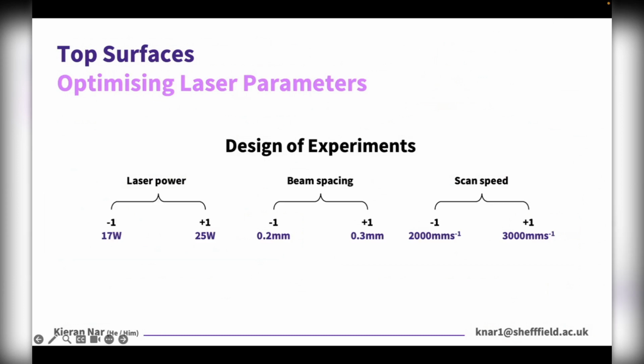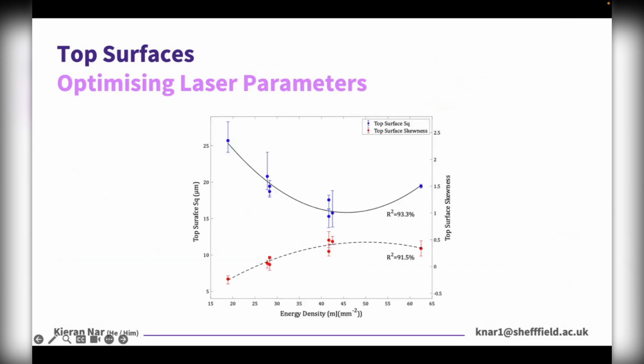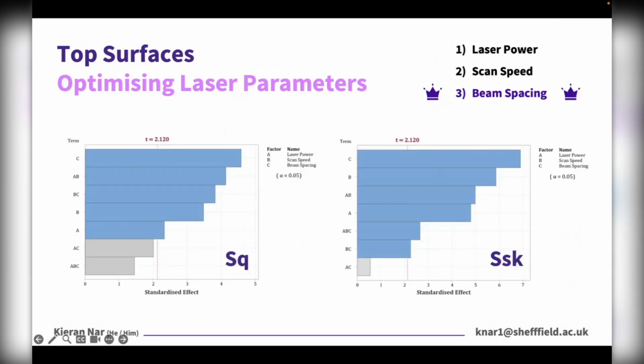And these were the parameters that we used to do so. And we found some interesting relationships, which I don't want to go into too much detail about now, but one of the interesting takeaways was that after performing some statistical analysis, we were able to determine that beam spacing was the laser parameter that influenced top surface RMS roughness and skewness most significantly.